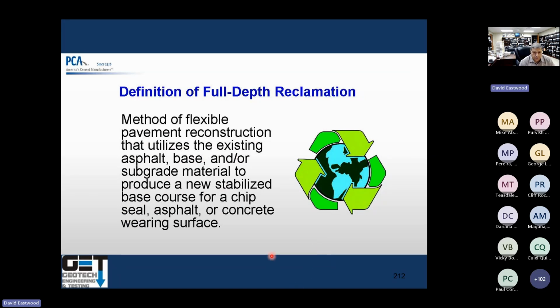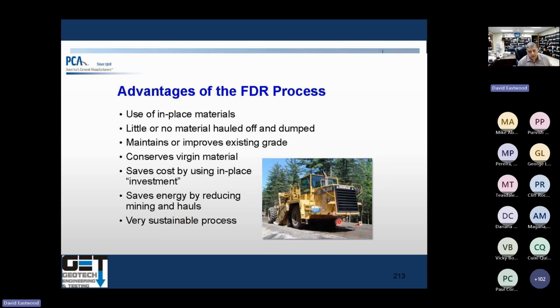Projects like this, you got asphalt paving. It's a method basically for asphalt paving and reconstruction. It uses the existing asphalt in the base and the subgrade, if it's stabilized, to produce a new stabilized base, and you put an overlay on top of that. Its advantages: you can use the on-site material and you don't have to haul in a bunch of new stuff. Not much material has to be hauled in. You put a new asphalt surface course on top of it.